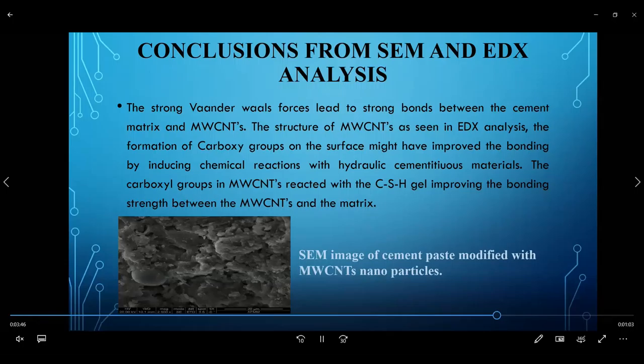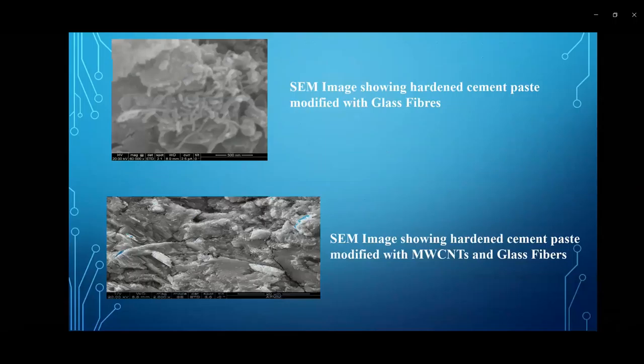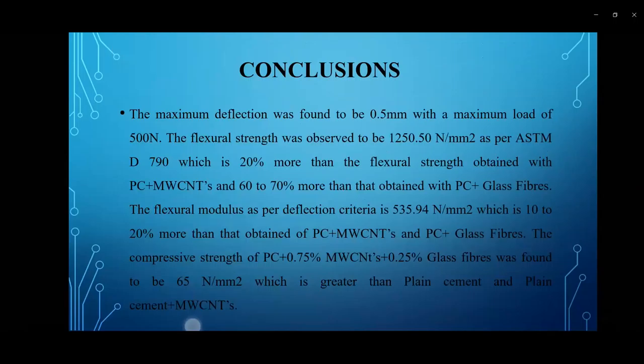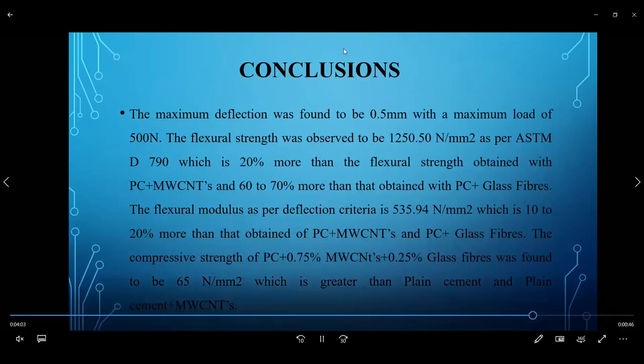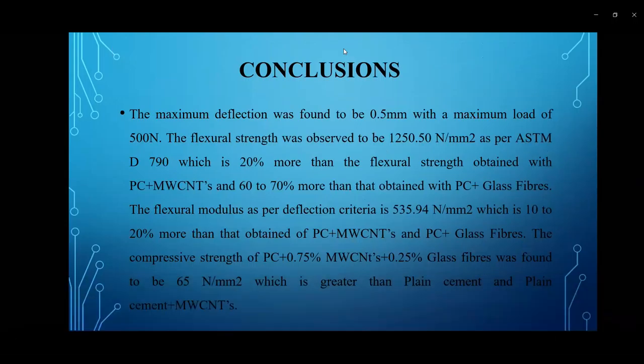So this is a SEM image of cement paste modified with MWCNTs nanoparticles. And this is a SEM image showing the hardened cement paste modified with glass fibers. SEM image showing the hardened cement paste modified with MWCNTs and glass fibers. The maximum deflection was found to be 0.5 mm with a maximum load of 500 Newton. The flexural strength was observed to be 1250.5 Newton per millimeter square.